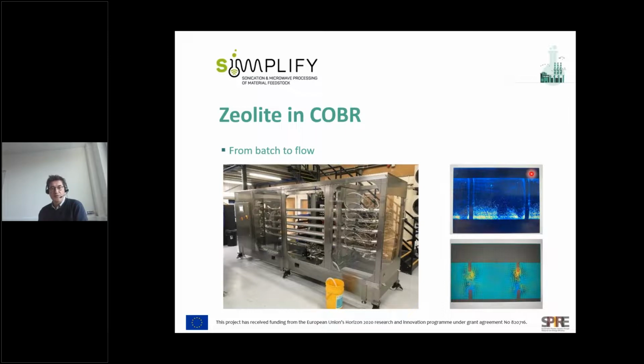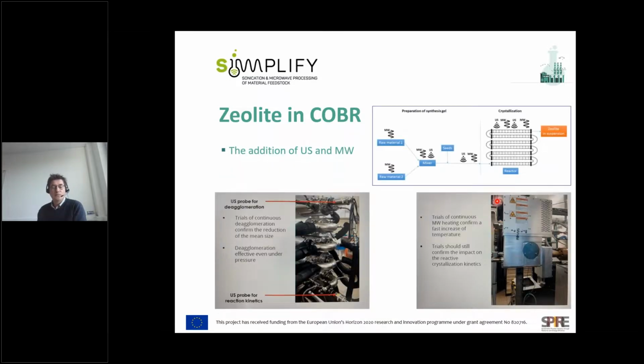We're looking at, for example, the fluid dynamics within the COBR, both by modeling, as you can see here, but also with experiments. For example, this is a picture from a PIV experiment, a particle image velocimetry system, where we're actually having solids in the liquid, and we can follow the trajectory of the solids while doing the pulsation in this OBR configuration. And so, as I mentioned before, we're now also integrating ultrasound and microwave at different locations in the system.